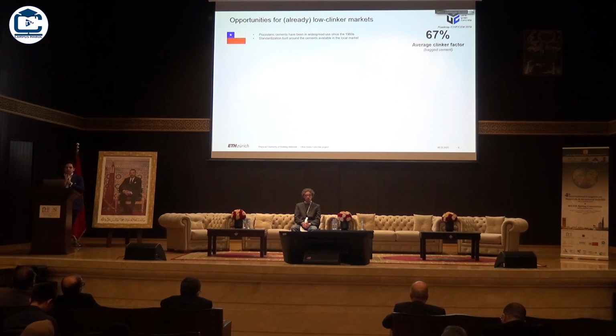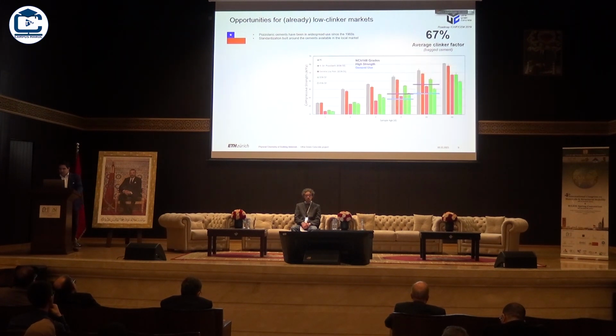And I will reintroduce the slide that Karen already showed with a little bit more detail. So, I'm originally from Chile. This is a country that is famous for its low clinker factor. It has today an average clinker factor of 67% in the bagged cement. This is not because the industry is particularly sustainably driven, it's basically because there is no limestone in the country and producing clinker has always been very expensive. So from a cost perspective, they have always been forced to introduce a large amount of SCMs in the cements that we use. And certainly the standards of the country are made around these pozzolanic cements.